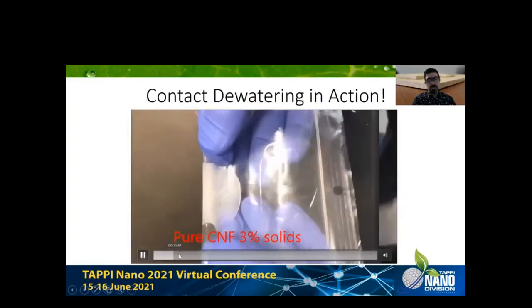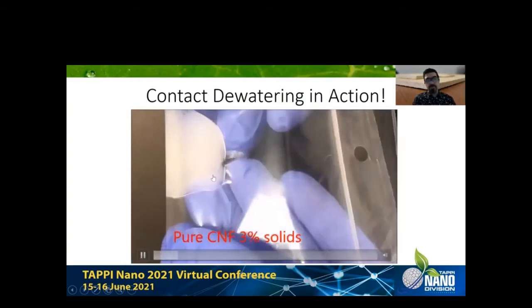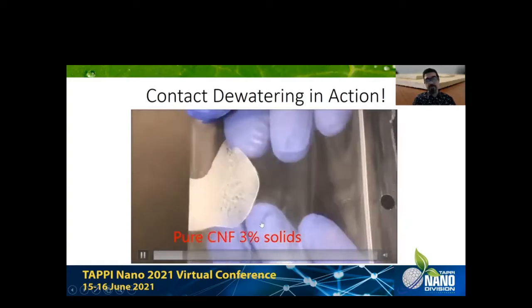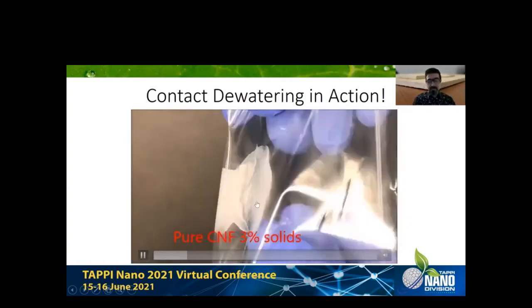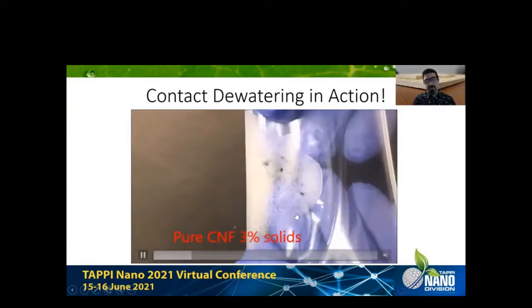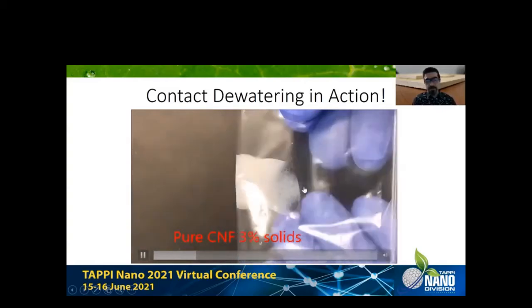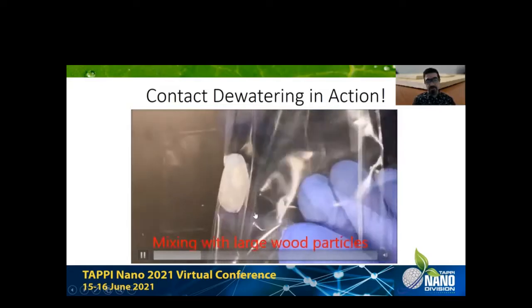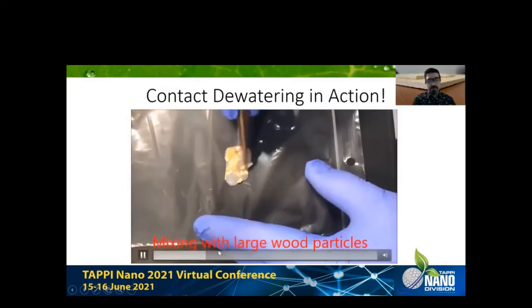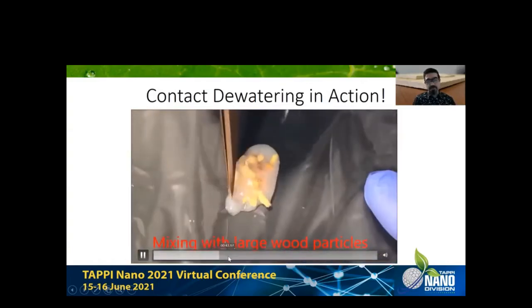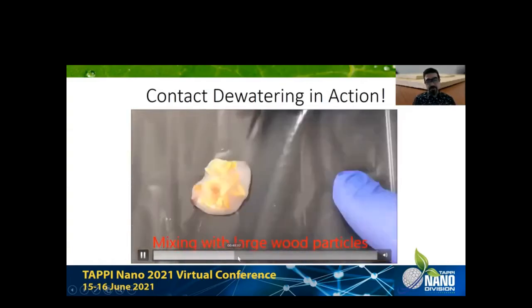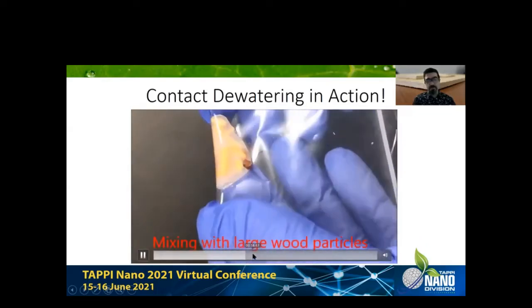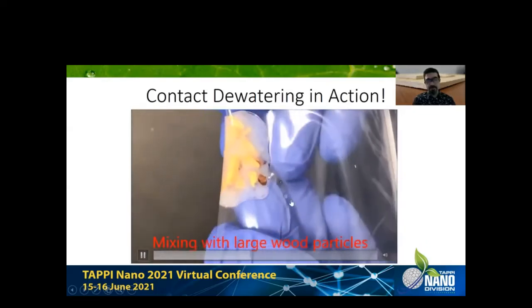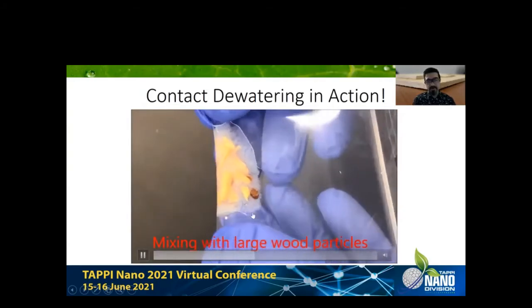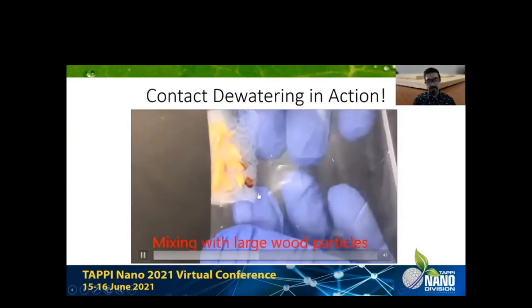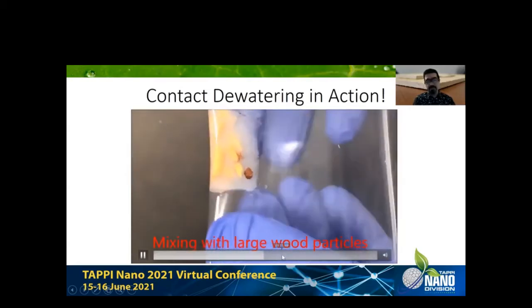So here, I'm trying to basically press or squeeze a small amount of nanocellulose inside the plastic film, just to put force on it and try to remove water from it. As you see, it is not possible to do that. Here, I'm adding a little bit of wood particles, larger pieces of wood particles to it, and then trying to do the same squeezing process and see if you can see any water coming out. As you see a little bit of water is being separated here on the side. It's not really that much, but you see there is something happening.